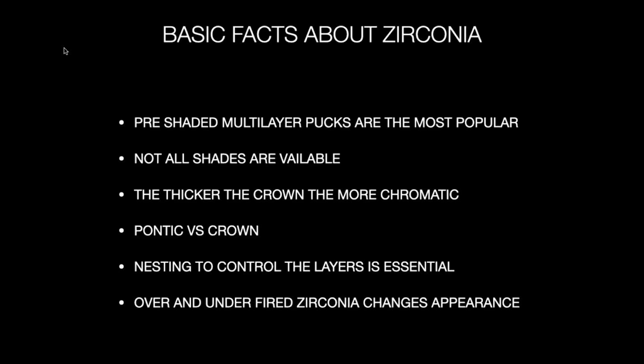Nesting to control the layers is essential. If you have a multi-layer puck, you have to remember what we do a lot of times is we go ahead and mill it, and we have a little finish line on the thinner crown. And then once everything is cooked, we look at it and say, okay, how close is it to the target shade? And if the Pontic is close to the target shade, I'll get some porcelain and build up the crown next to it if you want everything to look the same. The other problem is if you over or under fire or under sinter zirconia, it changes the appearance a lot. So you could have the best zirconia in the world, but if you don't fire it properly, you're screwed.